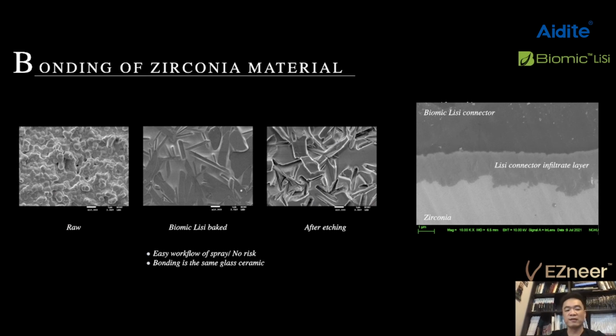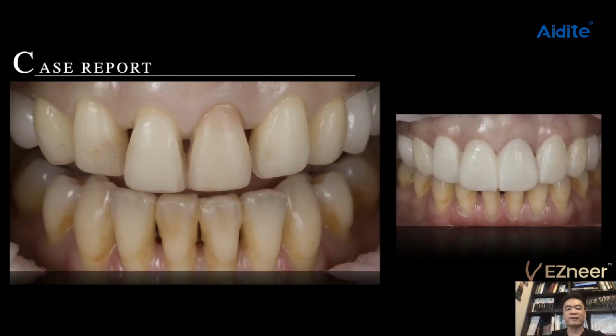So you can see this is the raw material on the Zirconia surface, and after this bake we supply the Lisi connector, and after Lisi connector etching, you can see the SEM photo. This is like the silicate and the glass ceramic surface. So this is interesting, and this is an easy workflow with no risk, and we also can get a very strong bonding strength, the same as glass ceramic with natural teeth. And this is the case report.